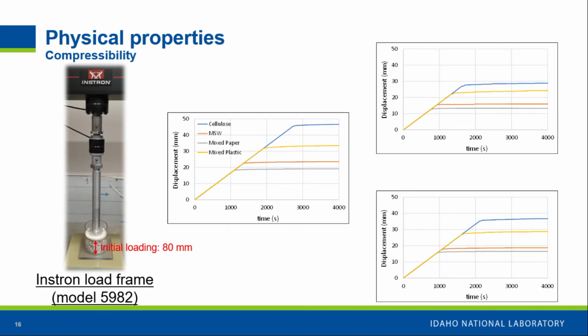So as we want to use our material as an insulating material, and if we put it into the wall, for example, we definitely don't want to change that material every year. So we wanted to see how that material compresses over time. So we did the compressibility test of the material. This test is a very short test, so we did it only for 1 hour to see whether we can see any change in the compressibility or not.